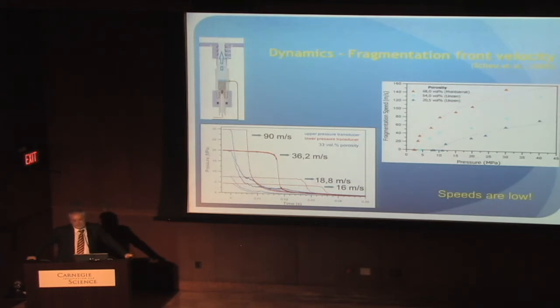So the process which effectively rips these materials apart involves more than simply sending the pressure wave through the sample. It involves deconstructing this material in a mechanical sense. We're talking about a world of failing bubbles with characteristic sizes and characteristic crack lengths that have to be achieved before the material is completely destroyed. The other point is the speed is so low. How can I get excited about a low speed talking about explosive eruptions? This speed is so low that we know from completely other sources and methods from petrology that magma can come up from depths within the earth at that speed. 10 meters per second is completely normal for an ascent rate of magma during a volcanic eruption.